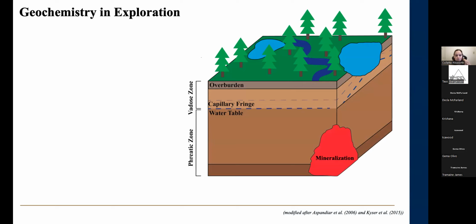And we use geochemistry as ore deposits are distinct geochemical anomalies that create a deviation in element concentration or isotopic signatures that are different from the geochemical baseline in an area. In addition to the main mineralizing zone, ore deposits are associated with primary dispersion halos, which occur with the original mineralizing system, and tend to be limited in extent and close to the ore deposit, except in highly fractured zones, which allows for dispersion to migrate a lot further.